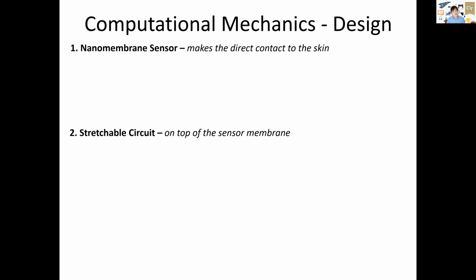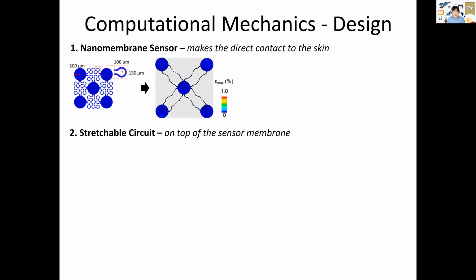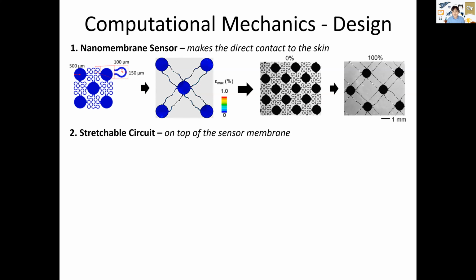So there are two major components, one nanomembrane sensor that makes direct contact to the skin. We wanted to make sure that the nanomembrane sensor is highly stretchable and flexible so that it can endure time dynamic changes of strain on the skin. And as you can see here, this nanomembrane sensor can endure the applied strain up to 100% without any mechanical fracture. And on top of this sensor, there's the stretchable circuit. It has less strain compared to the sensor because there's a strain decoupling chamber between the circuit and sensor.